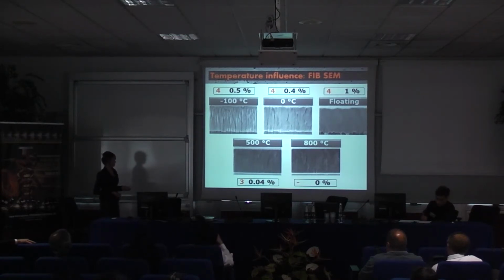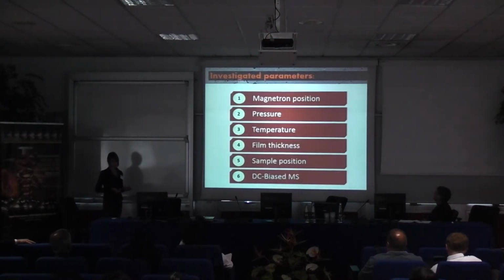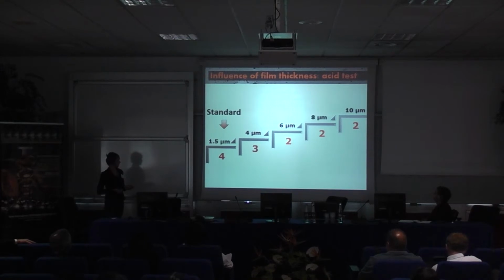Here you can see the cross sections obtained by scanning electron microscope, and it can show you that in the case of films deposited at low temperatures, also the microporosity, the voids inside the film microstructure, can also influence the general porosity of the film. We have investigated the film thickness depositing films higher than 1.5 micron, and we have seen that the porosity decreased a lot, but even the film with 10 microns of thickness is still porous. It means that there are probably macroparticles during deposition that are bigger than 10 microns.